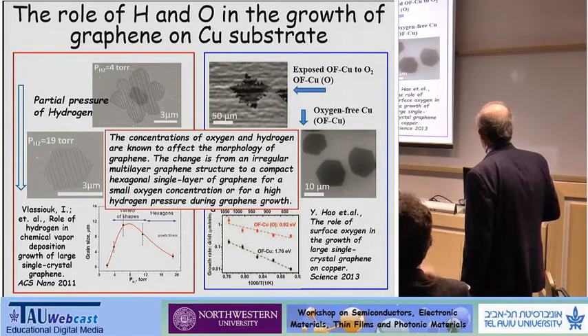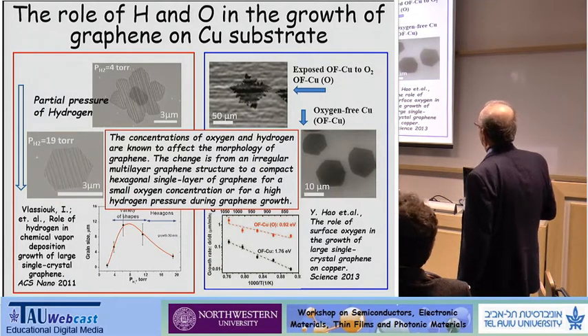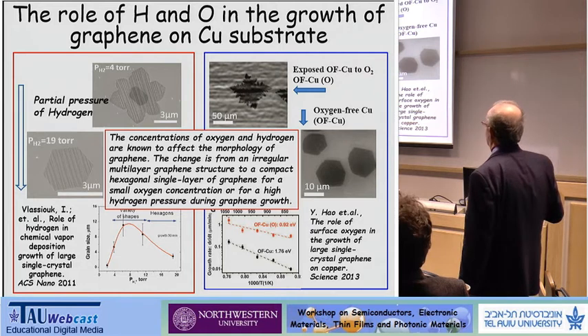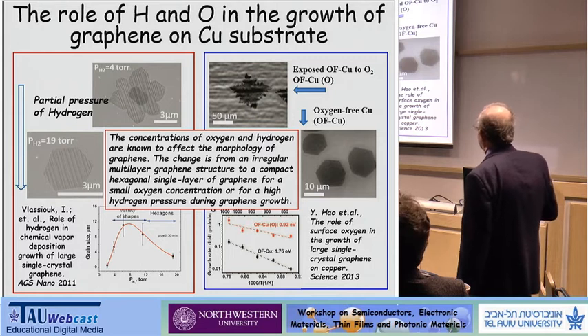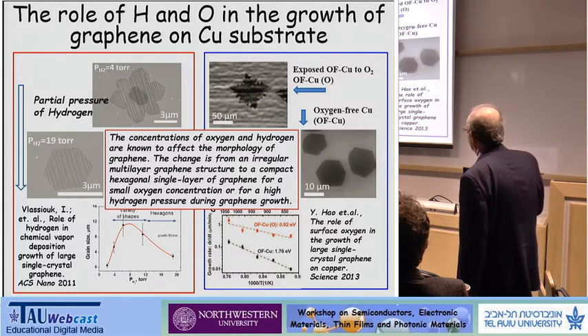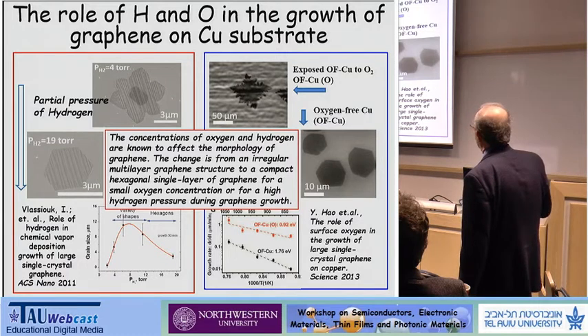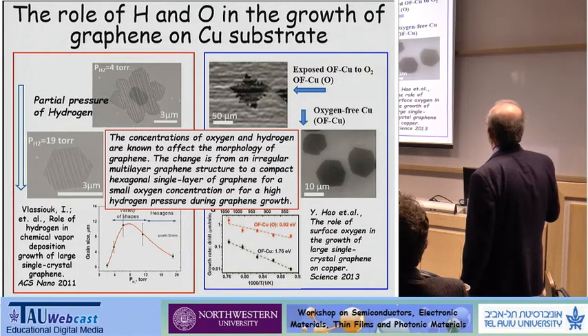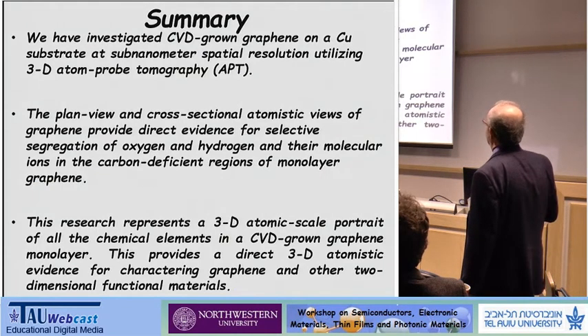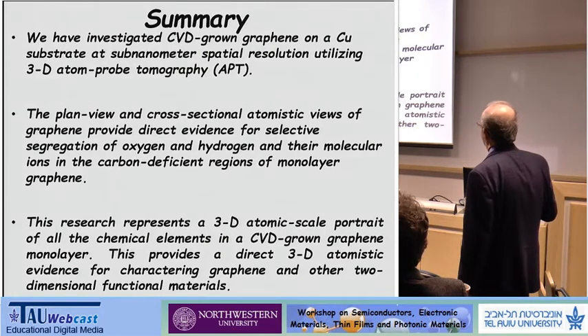This work is not ours. This is from fairly recent literature. When you grow the graphene, the partial pressure of hydrogen and the partial pressure of oxygen are quite important. And the key point is here that for small oxygen concentration, you get hexagonal-shaped regions like this. And for a high hydrogen pressure, you also get hexagonal-shaped regions like this. And the exact morphology that you get of the graphene depends on the hydrogen partial pressure or the oxygen partial pressure.